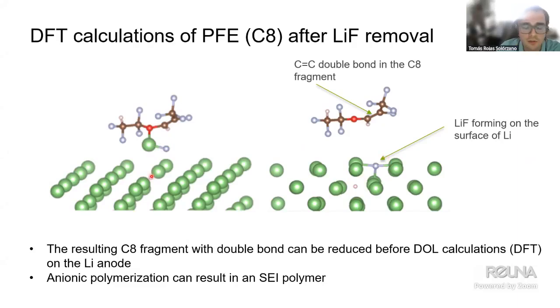And what happens also is that it pushes the hydrogen deeper into the surface, meaning that this will give us hints that there is formation of lithium fluoride over the surface of the lithium and a formation of a carbon-carbon double bond compound over or in the vicinity of the surface. This will give us two important conclusions.